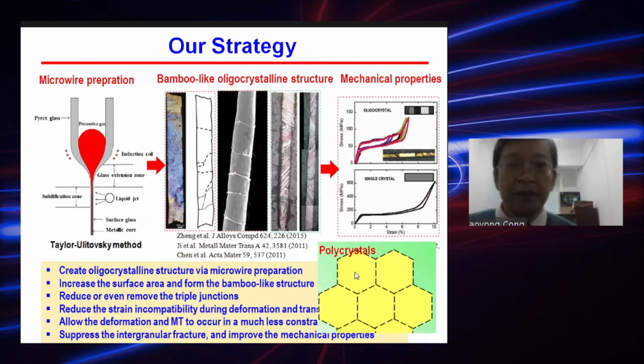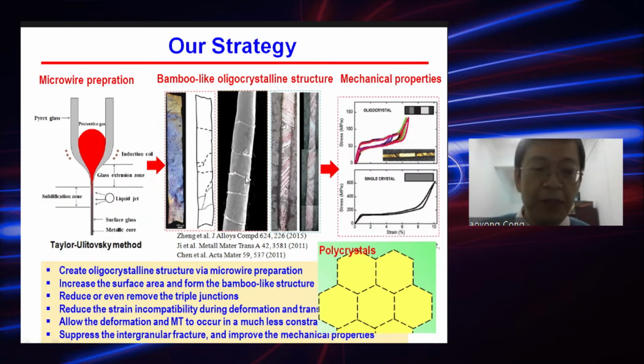We know that in polycrystals of magnetic shape memory alloys, during the phase transformation, there is strain incompatibility at triple junctions or along the grain boundaries. So it is very easy to form stress concentrations at the triple junctions and the grain boundaries, and thus during loading, cracks can easily occur along the grain boundaries or at triple junctions, leading to a brittle intergranular fracture. But with this kind of oligocrystalline structure, because the surface area is large, there are only a few grains in the sample, and it has bamboo-like grains. Therefore, we can reduce the strain incompatibility at grain boundaries during both deformation and stress-induced phase transformation. This allows the transformation and deformation to occur in a much less constrained environment. And therefore, the intergranular fracture can be suppressed, and the mechanical properties can be improved.